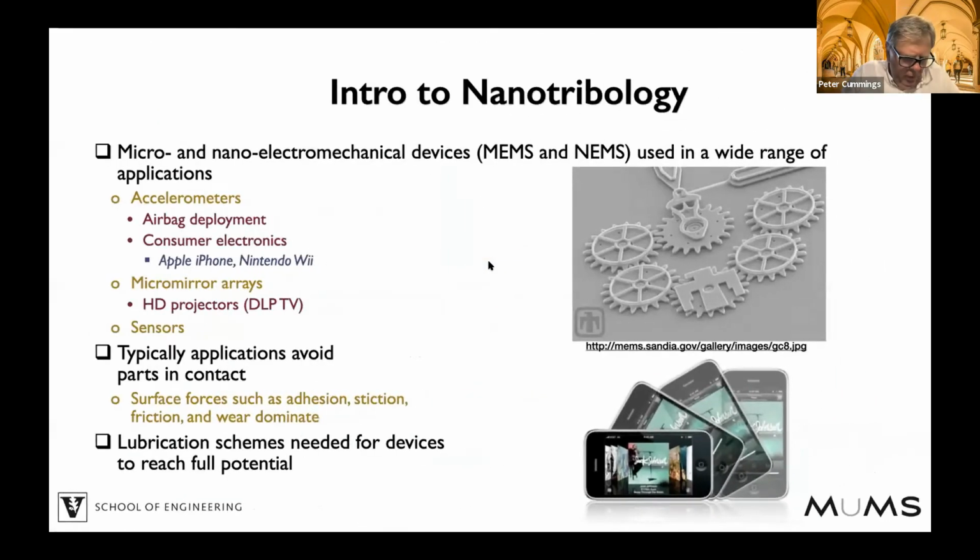So I want to now talk very briefly about a couple of applications. One is nanotribology. This is relevant in the lubrication of nanoscale devices when you have two surfaces moving with respect to each other at distances of the order of nanometers. How do you lubricate those kinds of systems? Traditional lubricants aren't going to work because, you know, an alkane, for example, will solidify when between two surfaces that are of the order of 1 or 2 nanometers apart.